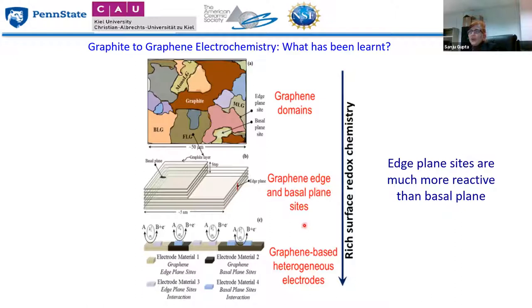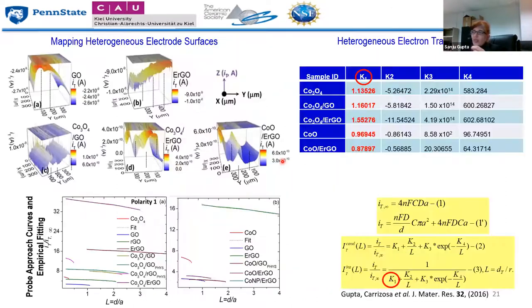Then of course, we wanted to expand our understanding from a fundamental perspective of what is happening at the electrode-electrolyte interface. So what we learned from the graphite electrochemistry, and then extending it to the graphene electrochemistry, is that the graphene surface or basal plane, as we call it, is not as electrochemically active as compared to the edges. And that is why these sort of morphologically controlled domains allow for higher electroactivity, so to speak. So we wanted to enhance the edge sites. So that's the idea, okay? So we use what we call scanning electrochemical microscopy, which I established in my lab when I was in, where this work was performed.